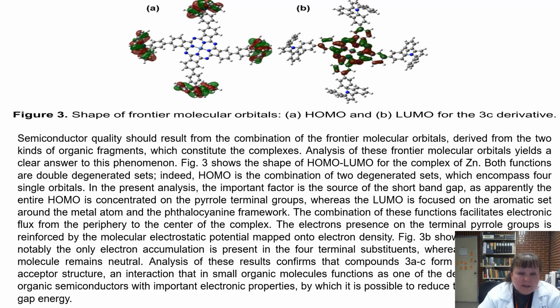In the present analysis, the important factor is the source of the short band gap, as apparently the entire HOMO is concentrated on the pyrrole terminal groups, whereas the LUMO is focused on the aromatic set around the metal atom and the phthalocyanine framework. The combination of these functions facilitates electronic flow from the periphery to the center of the complex. The electron presence on the terminal groups is reinforced by the molecular electrostatic potential mapped onto electronic density.